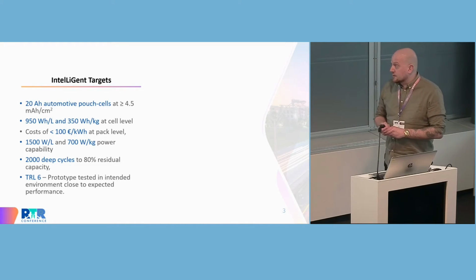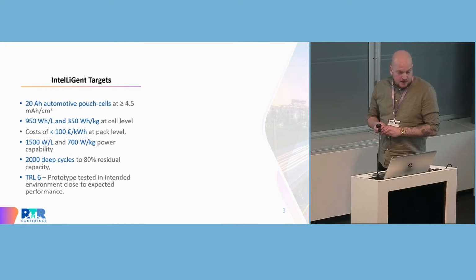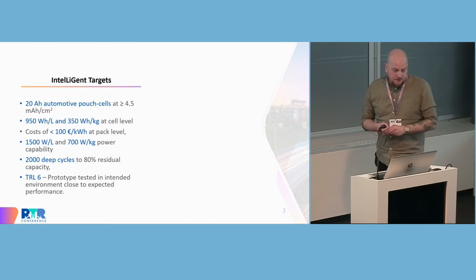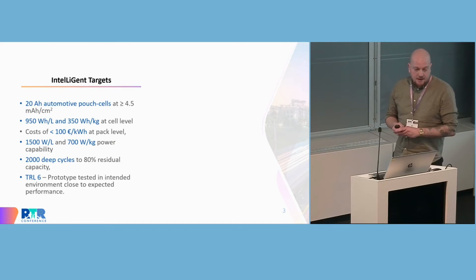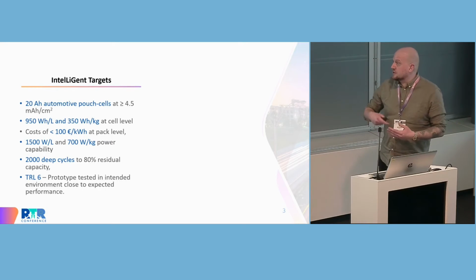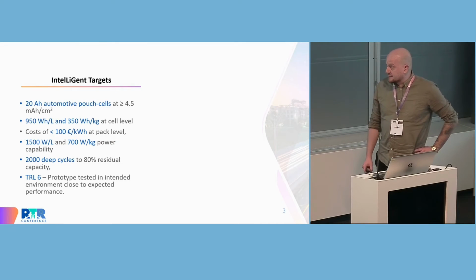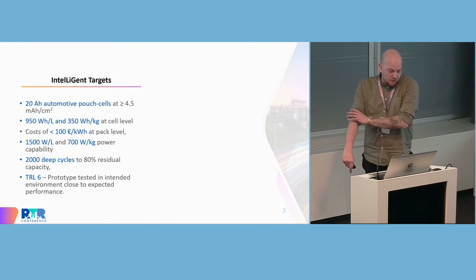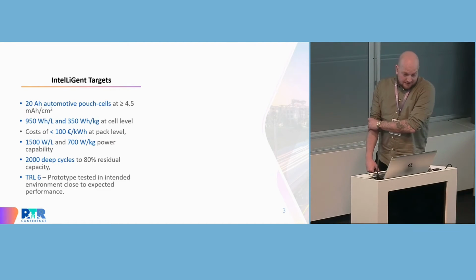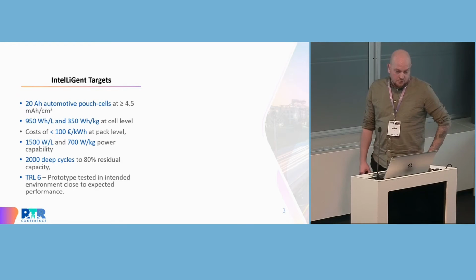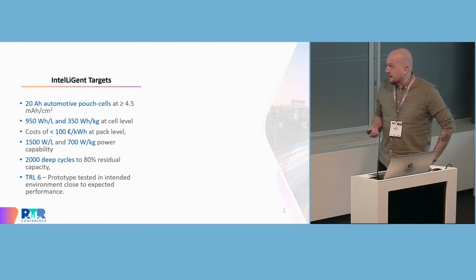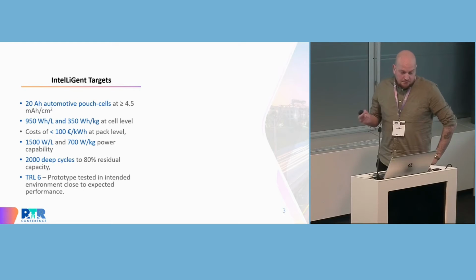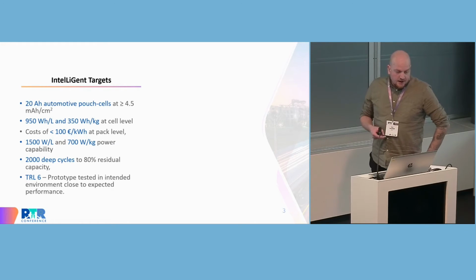However, at the end, we want to showcase this cell in 20 ampere-hour automotive pouch cell formats with high loadings beyond 4.5 milliampere hours per square centimeter, and also reaching a very high energy density at cell level of about 350 watt-hours per kg or 950 watt-hours per liter. The price tag should also be below 100 euros per kilowatt-hour, and we also have high charge or power capabilities as a target, and the cell should withstand 2,000 deep cycles, up to 80% residual capacity.